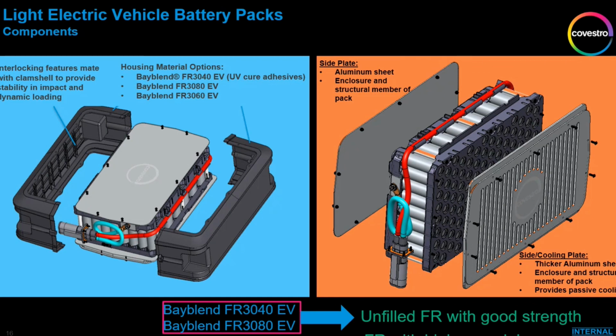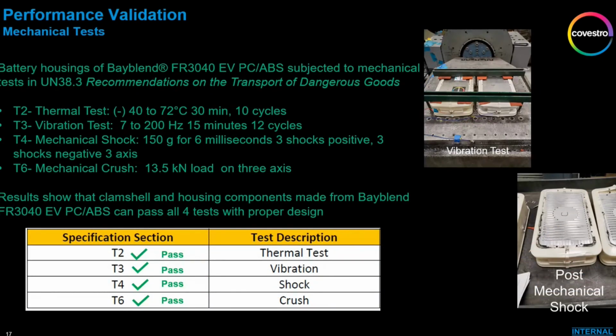The other major components that we designed in our materials are the housings. You can see here on the left, the upper and lower housing. Those were tried in several different materials, but we're going to focus mainly again on Bayblend FR3040 EV. And that is a very common workhorse material, but depending on the properties that you actually need for the application, you could look at another grade like Bayblend FR3080 EV, or if you need some higher modulus, Bayblend FR3060 EV, which is a 15% glass reinforced flame retardant material.